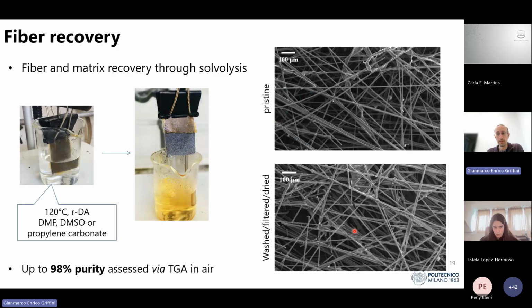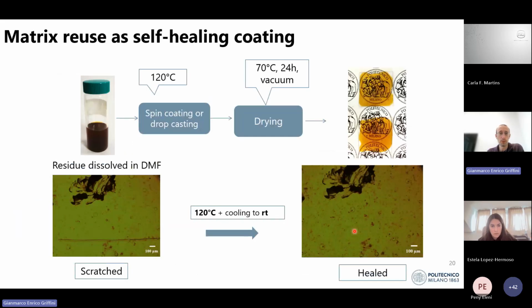We obtained clean fibers after recovering, cleaning up and washing steps, and the organic fraction was used to deposit a coating that could potentially be used as a corrosion-resistant or corrosion protection coating, which is also self-healable. You see here a scratch that was produced on the surface of the coating, and upon heating and cooling down, we could obtain a complete healing of the cut itself.